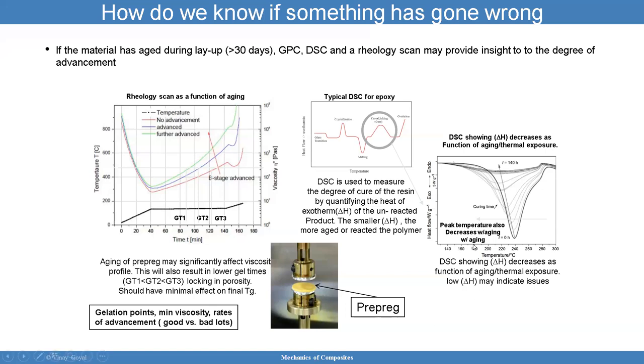Here, you can see how peak temperatures also decrease with aging. You can see the DSC showing delta H decreases as a function of aging and thermal exposure. So you can see that these factors can affect the delta H. Delta H decreasing as a function of aging and thermal exposure can indicate issues, right? So if I have a low delta H, then that could mean I have some sort of issue going on.